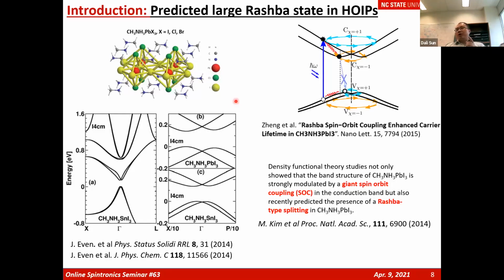And later on, people even use the same concept to describe why the photoconversion efficiency is high in the Rashba materials, in the hybrid perovskite materials. The reason is forming the indirect band transition. Once you're forming indirect band transition due to Rashba effect, you're forming the excitons. The recombination rate for the excitons will be reduced because the indirect transition is forbidden by the spin selectivity rules. So that's what causes your exciton and carrier diffusion length to be extremely long and might be responsible for the high efficiency for solar cell.